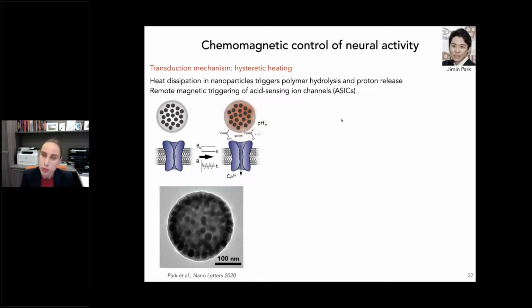But liposomes are not the only objects that we can control through a local temperature increase in magnetic nanoparticles. For instance, we can surround our nanoparticles by polymers, and we can tune the chemistry of those polymers such that their hydrolysis will be controlled by a temperature increase at different rates. And if we can control polymer hydrolysis, that means we can control proton release. And if we can control proton release, that gives us control over pH.